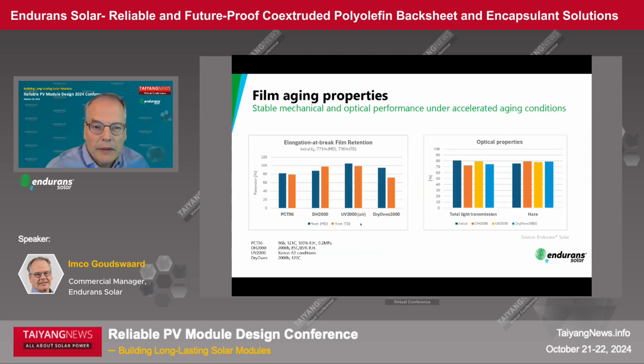These are some development results we did on purely the film, so not laminated yet. It's aged under different circumstances: UV, humidity, pressure cooker test. Then we always look at whether something changes in the polymer structure, and that's best shown by the elongation at break. You can see here that after these aging periods, we had a reduction of, let's say, something like 20%, which is very much acceptable. And on the right side, optical properties are of course also very important, and we did the same aging tests on the samples and checked optical performance, where there's also little change, or still a lot of retention, after these aging times. Next slide.